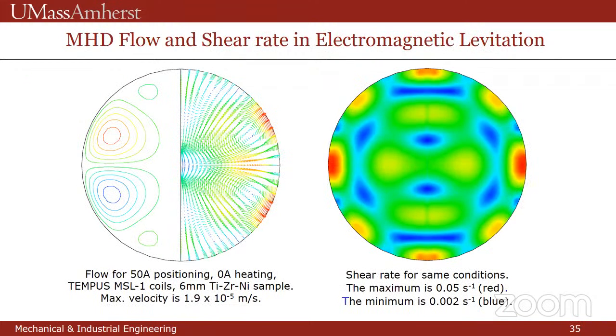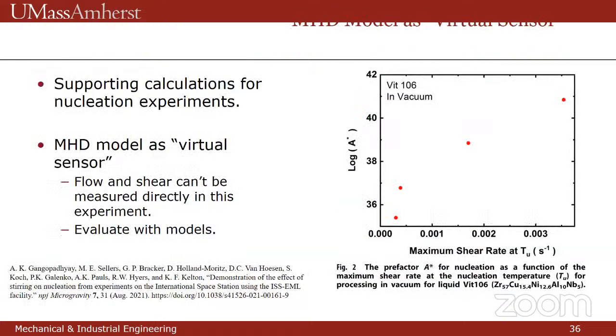So here is some colorful fluid dynamics about the flow in these levitated drops. These drops are symmetrical, which is characteristic of drops in zero gravity. And in this case on the right, we've plotted the shear rate. So it turns out that the shear rate in the flow determines the extent. And so this information can be combined with results from time to solidify to get plots like this. So the left axis is the pre-exponential factor in the nucleation equation, and the bottom axis is shear rate, that's ours. And this appeared in a paper in npj Microgravity.